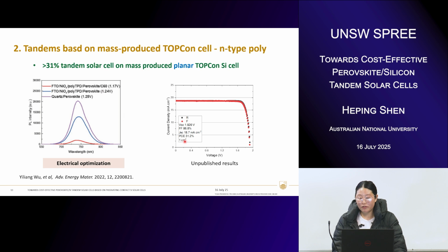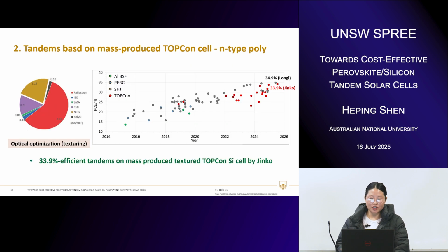One of the notable metrics here is a very high fill factor. We achieve almost 87% fill factor in these high efficiency cells based on commercial mass-produced TOPCon cells. I believe that should be among the highest that has been reported. Okay, so that's the electrical optimization. And